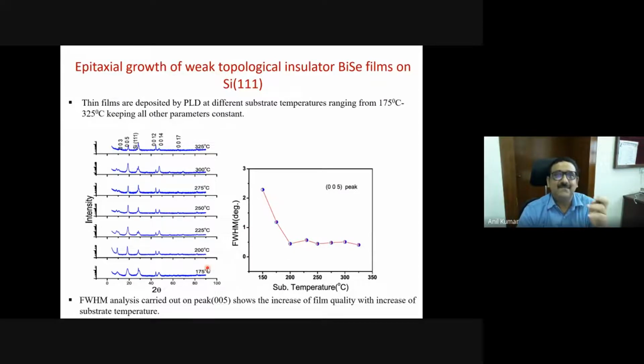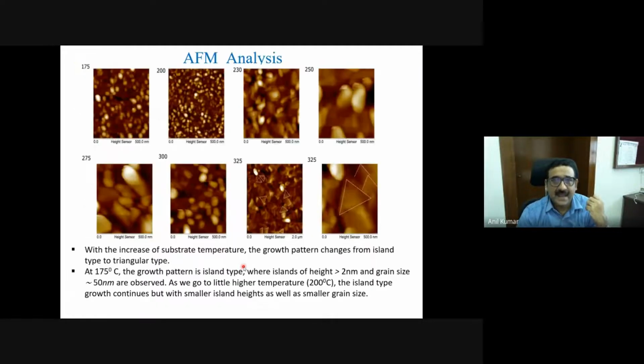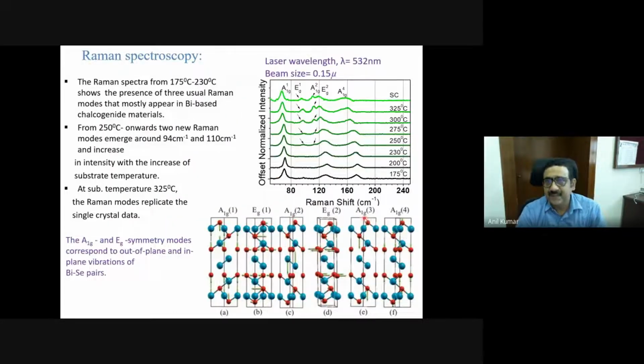And what we do, we grow the thin films of this BiSe on silicon substrate by PLD. I saw in this video which was playing that you have a PLD system there. So we also grow these crystals by PLD at different substrate temperatures. And then we look at the AFM analysis, you get this triangle-shaped thing at the appropriate temperature. So we have a very good film, and we confirm the quality of the film by Raman spectroscopy.